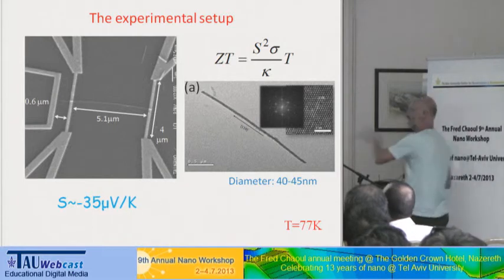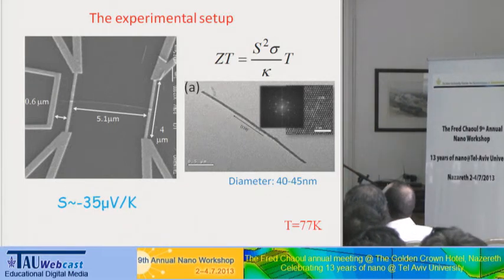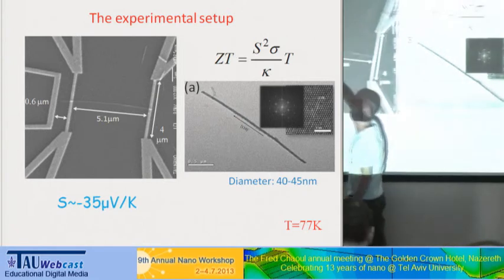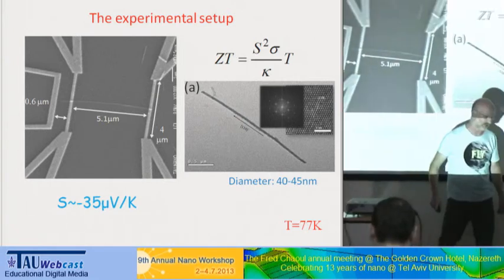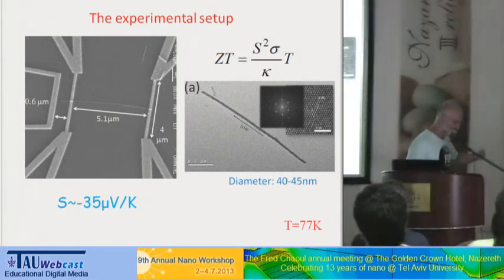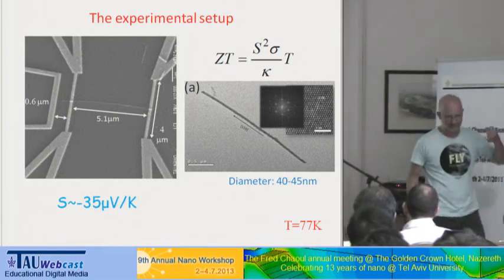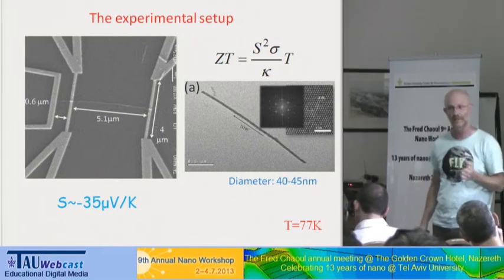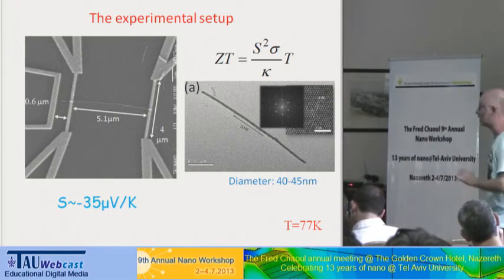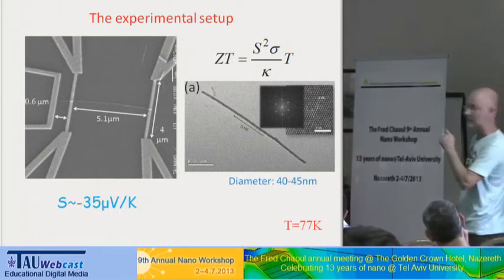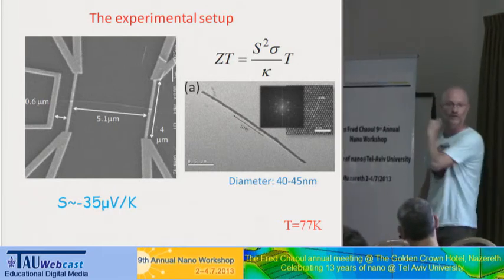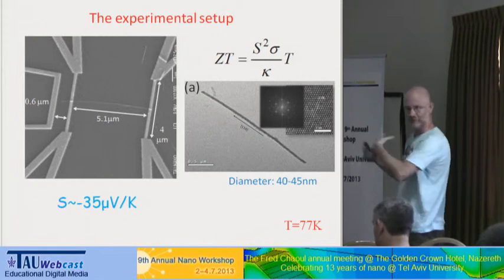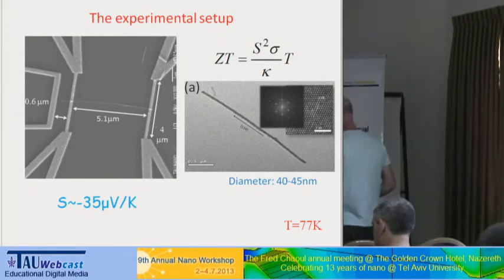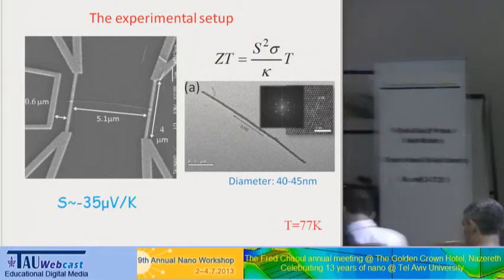Now, in order to make this experiment, you need to have really good ohmic contact on both sides. It turns out that making good ohmic contacts with bismuth is a very, extremely complicated process because of the oxide which is covering bismuth. It took us 2 years to solve it, just to give you a feeling of how difficult this is. So once we have the contacts, what we can do is the following.